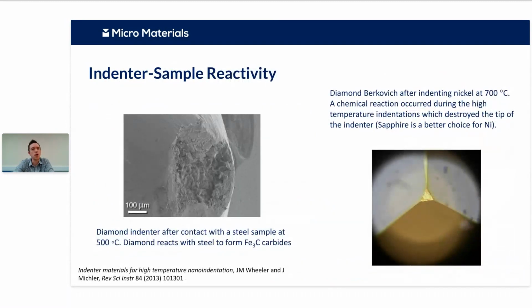So in addition to oxidation, this was also alluded to in Dr. Raturi's talk, we have to consider any potential reaction between the indenter tip material and the sample material. So with nanoindentation, we are generating very high contact pressures. So when we combine that with high temperature, we have the conditions for a possible tribochemical reaction between the tip and the sample. So the most common example of this is when we are indenting steel with a diamond indenter.